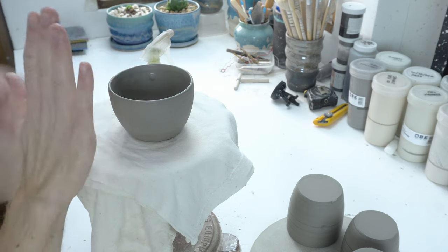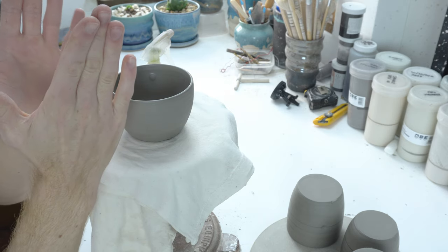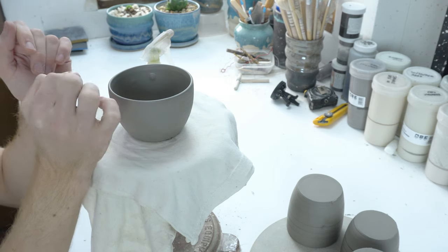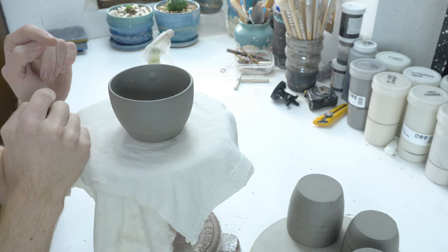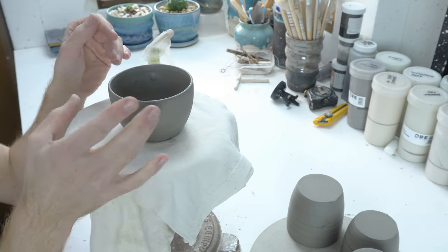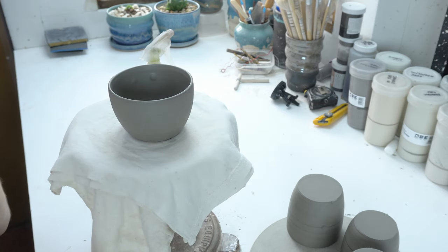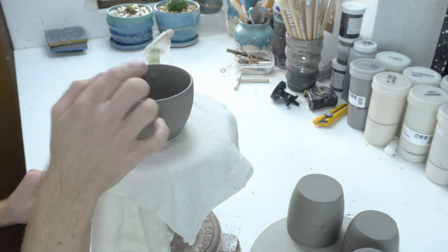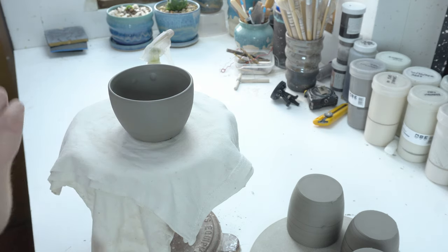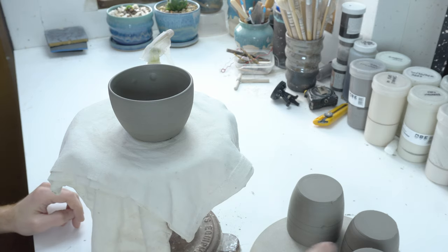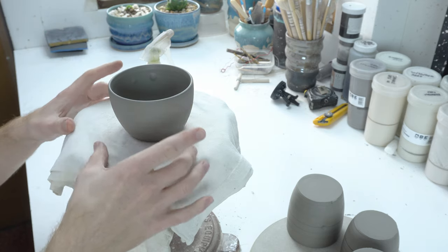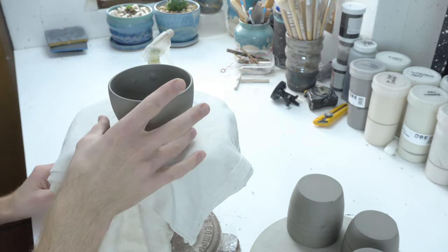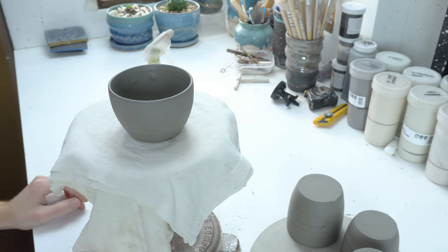What's happened is the water has absorbed into primarily the first kind of half millimeter of the clay on the inside. And that clay is now slightly wetter than all the rest of the clay. If you left this for long enough it would even out, but for now that clay is wetter. So give it kind of a minute or two. What I do is if I've got a bunch of pieces I'll go round misting them, setting them back. Obviously don't set them on the rim while the rim is wet. Just leave them like that for a minute or two.